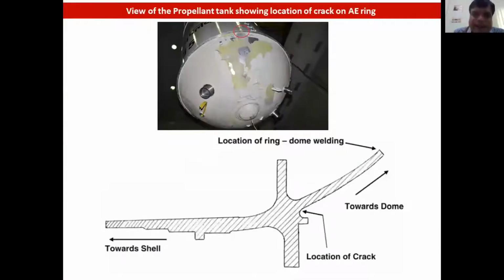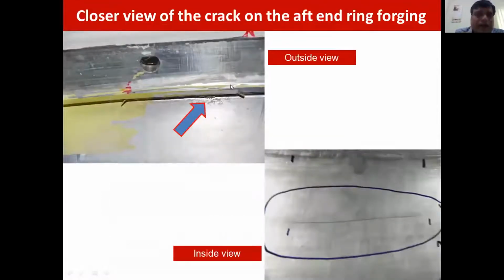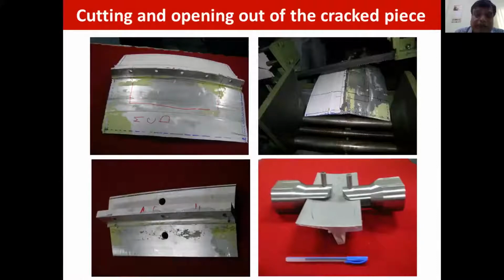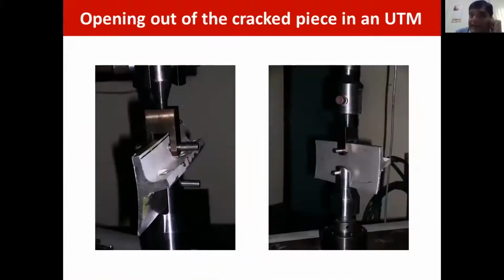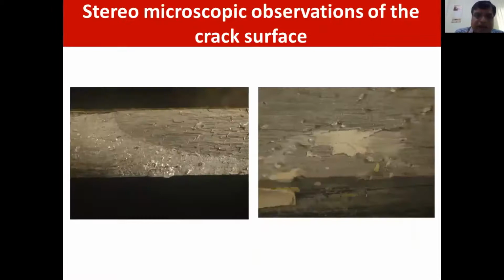So we brought the tank, and this is the configuration, and you can see the location of the crack. This is the D5 propellant tank, and the location of the leak is indicated in red. We saw a 300 millimeter long crack on the aft end ring of the forging, and this is the location from where liters and liters of propellant were leaking, as you can see from the white smoke in the first photograph. Then we tried to open the crack. Because the propellant tank is several meters long, it has to be sectioned and we have to carefully open it. So we put in drill holes and opened it without touching the fracture, and we successfully opened it in this UTM. And this is the area that has shown the pre-existing crack.